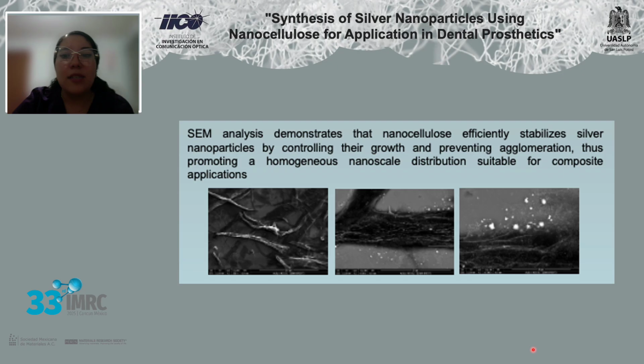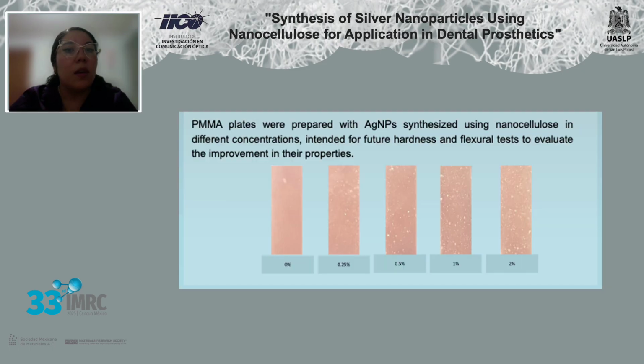The SEM analysis revealed that the nanocellulose prevents agglomeration of the nanoparticles, achieving homogeneous distribution at the nanometer scale. We can see the fibers of the nanocellulose and we can see the nanoparticles in this part. PMMA plates were prepared with nanoparticles using nanocellulose in different concentrations, and these were ready for future mechanical testing.